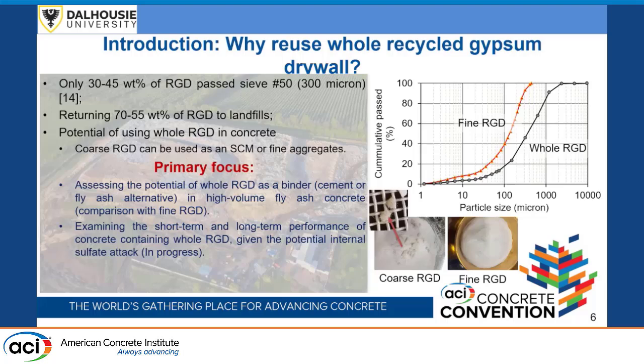So what's the problem with using fine recycled gypsum drywall? The primary issue is that only 30 to 45% of the RGD would pass sieve number 50 and have a compatible particle size with the cementitious materials. So by just using fine recycled gypsum drywall, we almost return between 70% to 55% of recycled gypsum drywall to the landfill, which could result in the landfilling issues and environmental impacts that we already discussed.